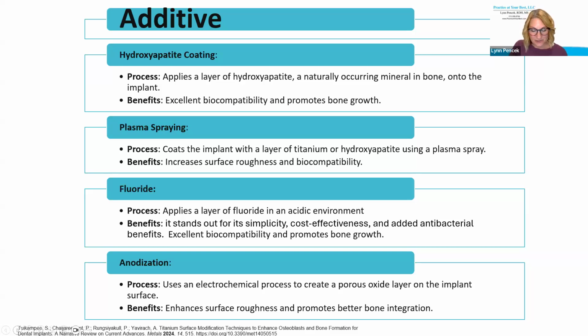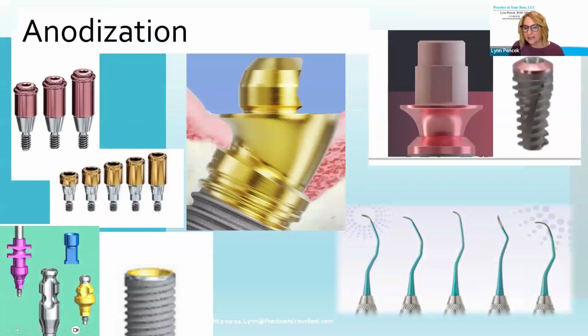And then there's anodization. And anodization is the introduction of the titanium into an electrochemical process. We take the implant, we place it into an acid bath, we give it some electricity, and it creates this nano surface texture. It creates a rough surface to promote better bone integration. And we notice with anodization, the titanium surface texture will change color over time. So depending on the amount of time of anodization, you may find the color changes to gold, to pink, to blue.